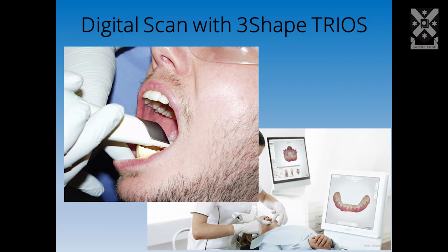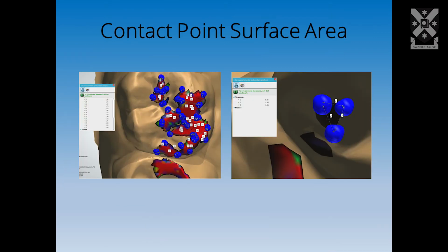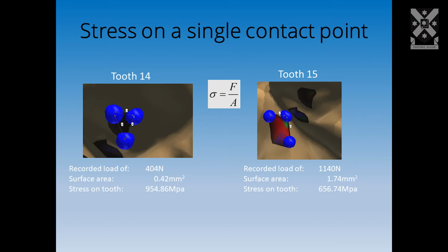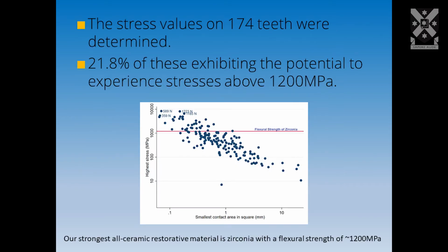And once we had done that, we then scanned the upper and lower teeth using laser scanning technology, and this gives a three-dimensional output, and that allows us then in the computer to calculate the surface areas of these contact points and contact areas. And once you know the force and once you know the area to which it's applied, you can calculate the stress. And of the 174 teeth that we measured,